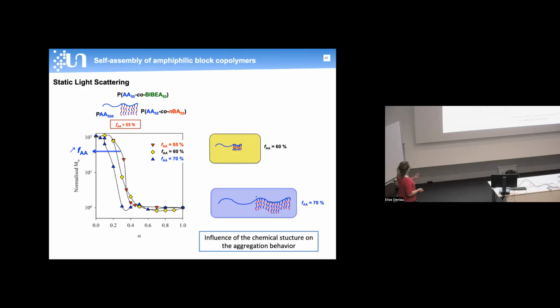And we play on the chemical structure of the bottle brush by varying either the volume fraction of the hydrophobic block brush or by increasing the length of the backbone and keeping the volume fraction the same. And we could see that the disaggregation transition could be tuned by increasing the molar fraction of acrylic acid units.